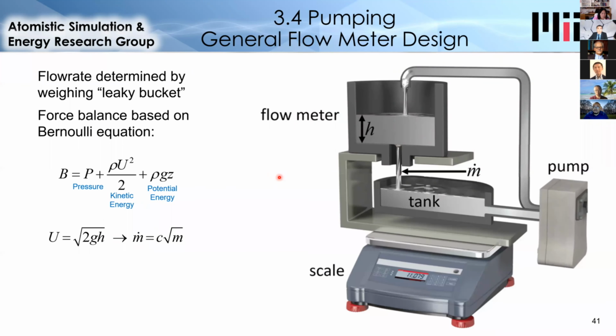So now that the pump geometry was designed, I needed a way to verify its functioning. And the way to do this is to measure its flow rate, but we couldn't use any commercially available technology because it's far too hot. So we designed a very simple flow meter, which is essentially a tank with a hole in the bottom of it, sometimes called the leaky bucket method.